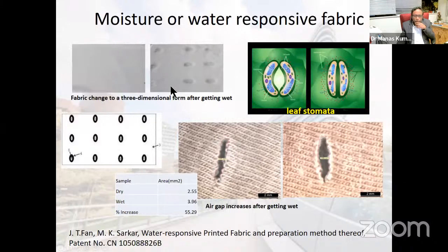And we have observed when this fabric is getting wet, these printed portions are changing from two-dimensional to three-dimensional. And that's the unique thing. So here you can see when it becomes three-dimensional, automatically its contact with the body would be reduced, and that gives you much more benefit. Because when we sweat, what happens? This fabric sticks with our body, and definitely we are not feeling good. But if this forms a three-dimensional shape, contact with our body would be reduced, and we can get much more benefit. So once we achieved it, after that, we tried to cut these portions using the laser cutter.